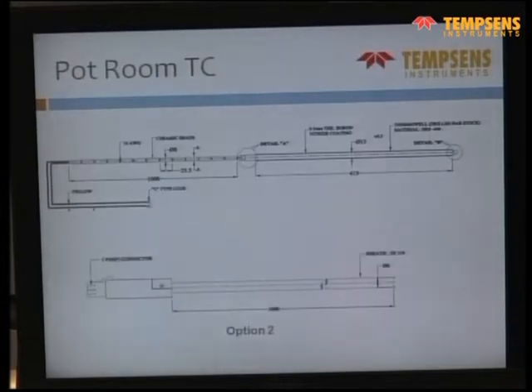In case of pot room, they are using 446 tube with boron nitride coating, and the thermocouple is bare wire or an MI cable, and you can see the tip at the bottom. They are pushing it inside the molten aluminium to take the temperature, and you can get maybe 30 to 70 dips of the pot temperature. Bottom is another option, which is using high wall thickness MI cable in SS304, and this is also for the same application of pot room temperature measurement in aluminum plant.